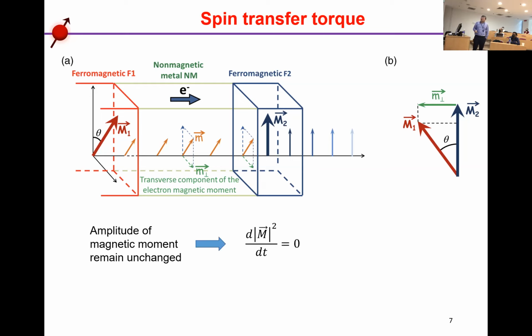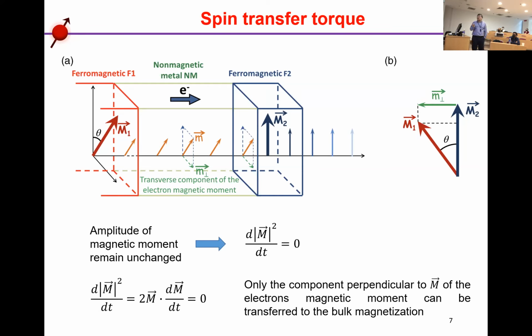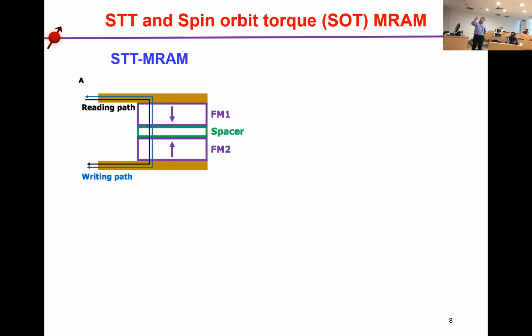So based on this, we have dm square, the amplitude of dm square dt, equals 0. Based on this, we can say only the component perpendicular to the m of the electron's magnetic moment can be transferred to the second ferromagnetic layers. That means the parallel component does not generate any torque on the second ferromagnetic layer. So when these two ferromagnetic layers are purely parallel or anti-parallel with each other, there's no torque. Okay, from here we can see this STT-MRAM has certain disadvantages.